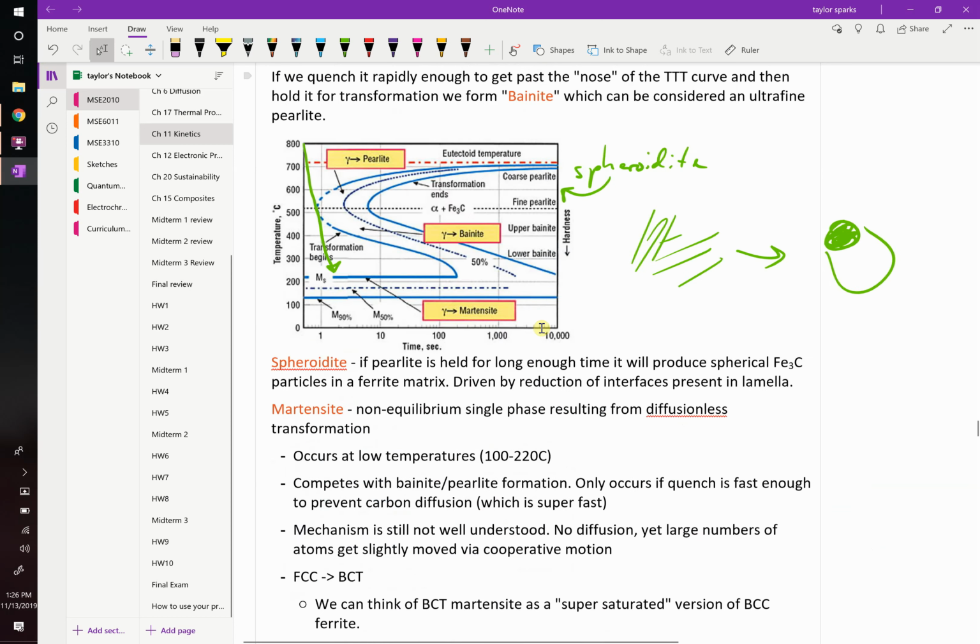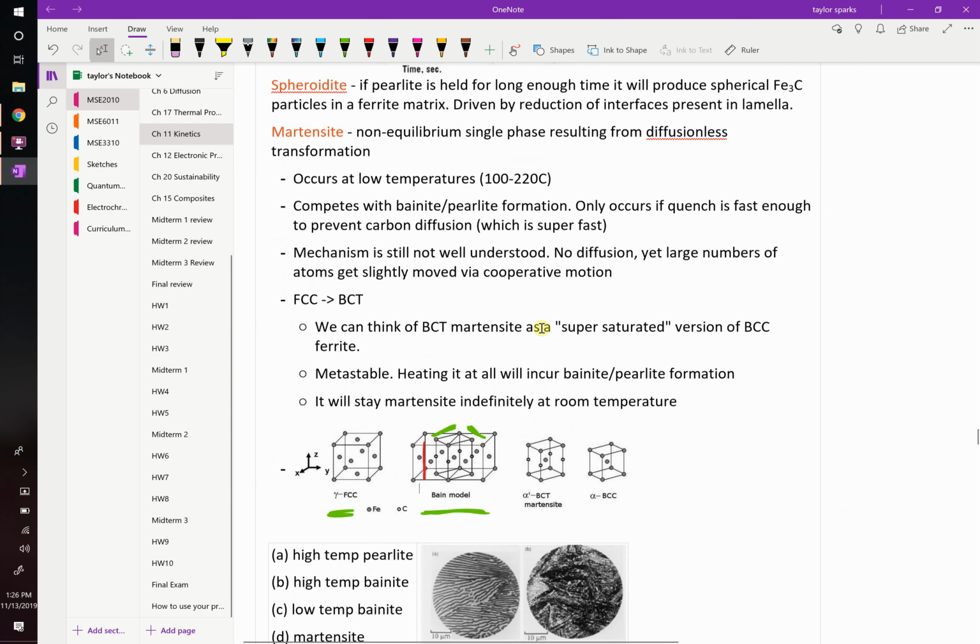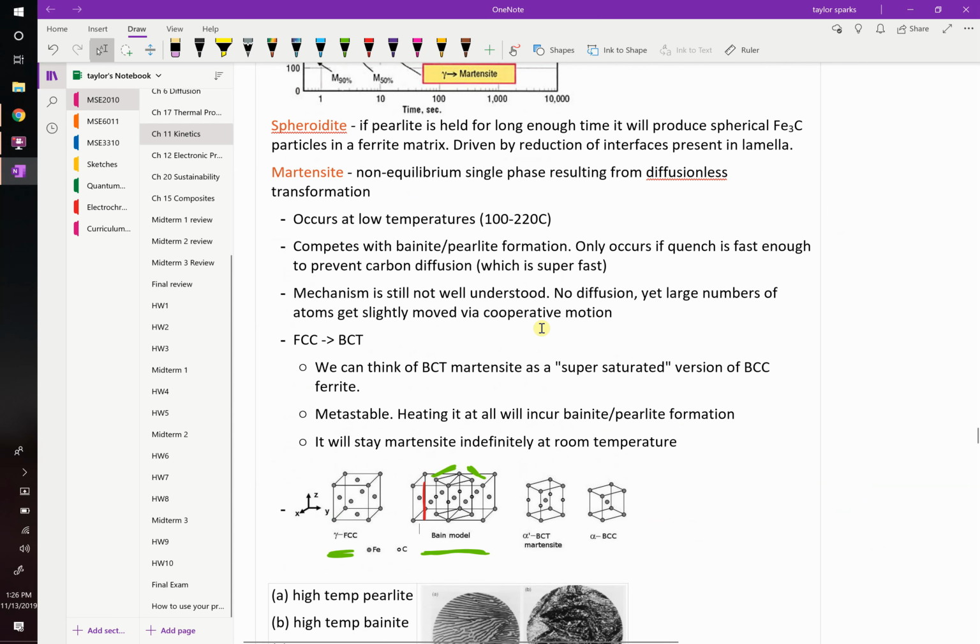So again, if this was our structure, we had this guy. Now we're going to heat it up at such a low temperature that the carbons can't form big sheets like the zebra stripes. Instead, they form little tiny precipitates. So those little tiny precipitates do a hell of a job to strengthen your material. So tempered martensite, you heal the cracks a little bit with this process, and you end up with sort of the best case scenario if you want to maximize both ductility and strength. You can't do better than tempered martensite. Okay? Can I answer any questions?